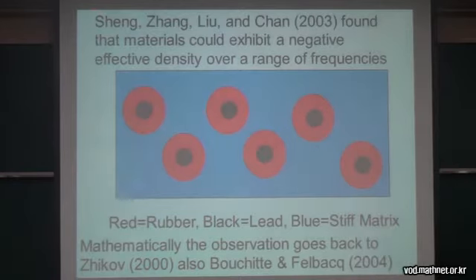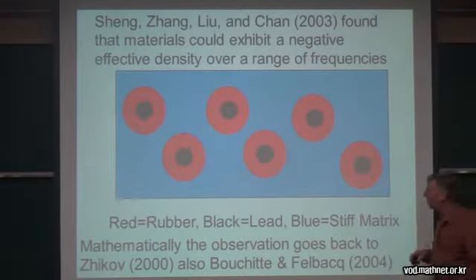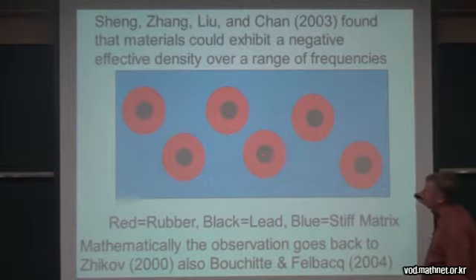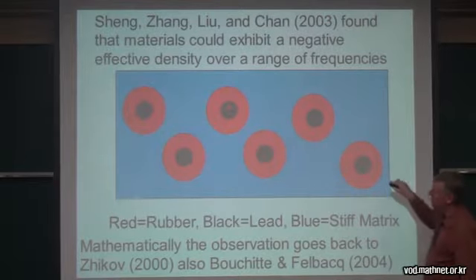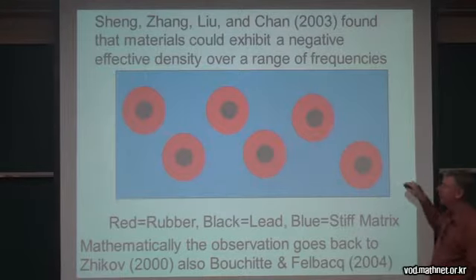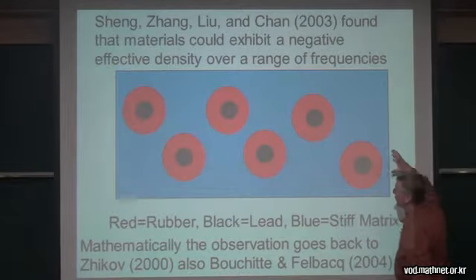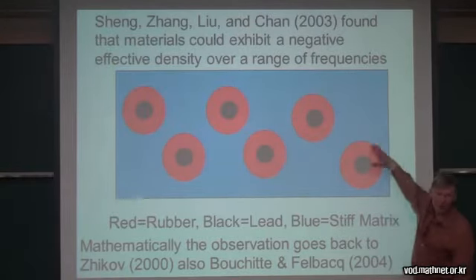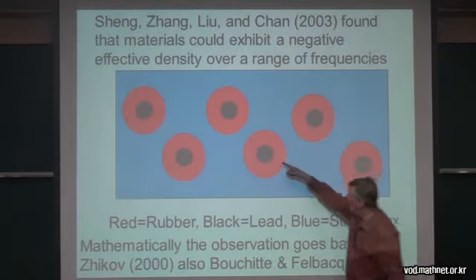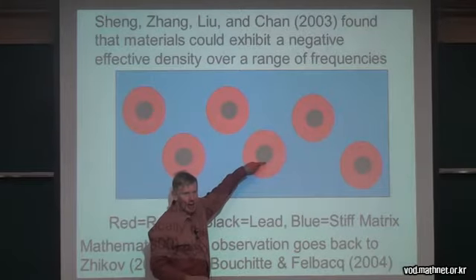And actually Sheng, Zhang, Liu, and Chan in 2003 found that materials could exhibit a negative effective density over a range of frequencies. And so this was an experimental result, but the geometry they basically had was lead balls surrounded by rubber in a stiff matrix. And when you oscillated this back and forth at a given frequency, there was a resonant frequency, and the lead balls moved out of phase with the motion of the surrounding background.